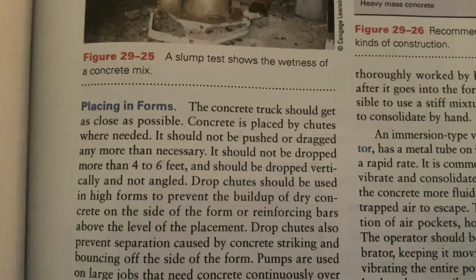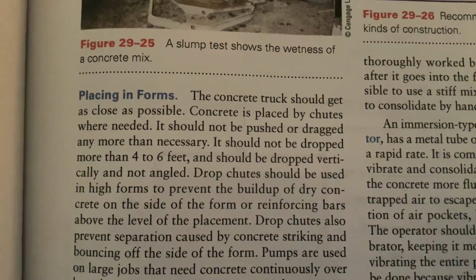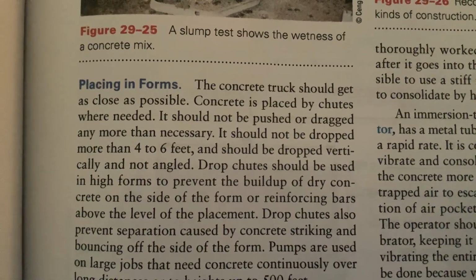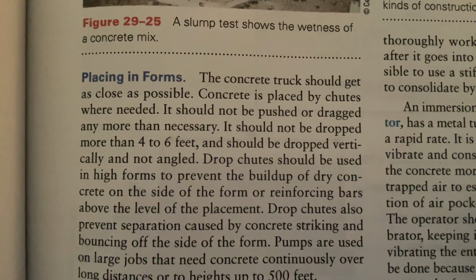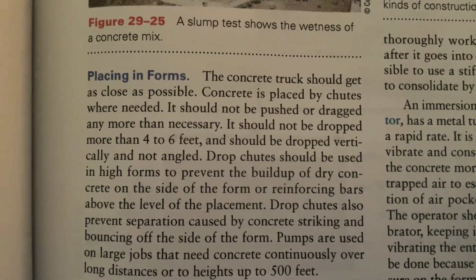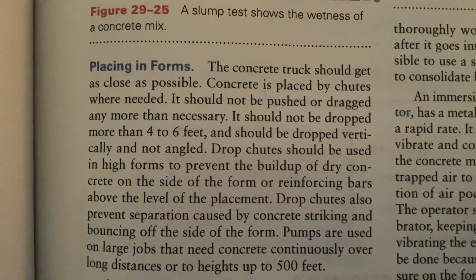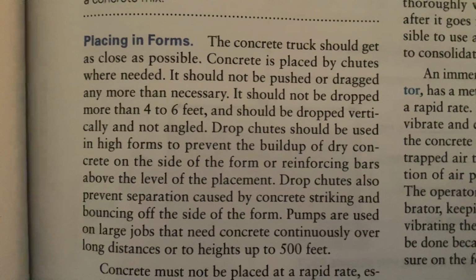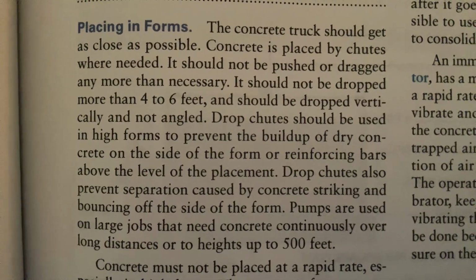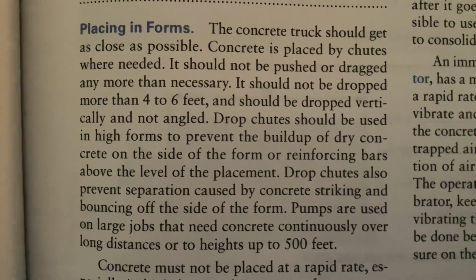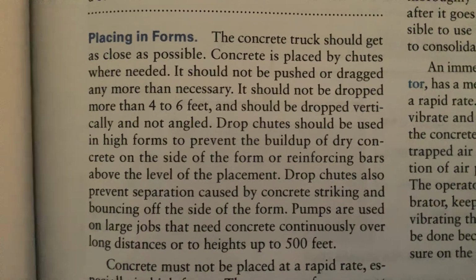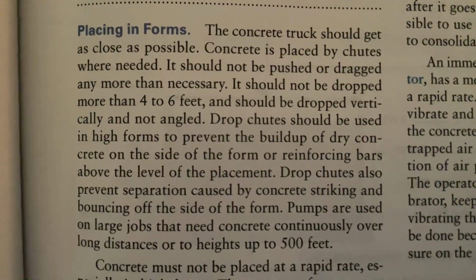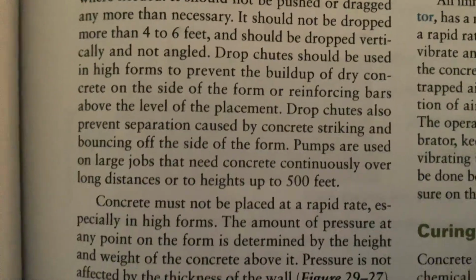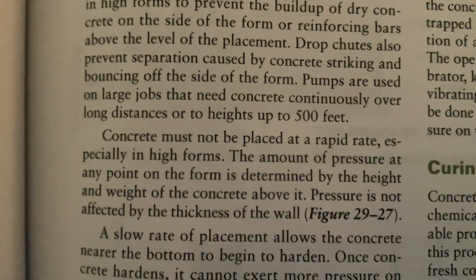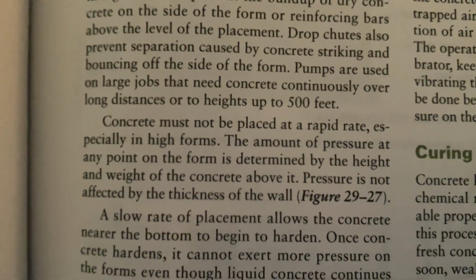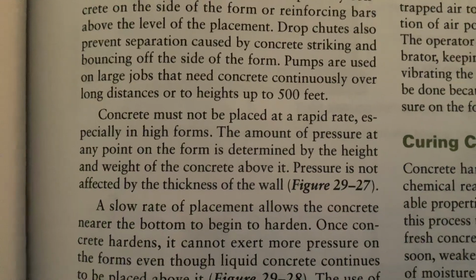The concrete truck should get as close as possible. Concrete is placed by chutes where needed. It should not be pushed or dragged more than necessary. It should not be dropped more than 4 to 6 feet, and should be dropped vertically and not angled. Drop chutes should be used in high forms to prevent the buildup of dry concrete on the sides of the form or reinforcing bars above the level of the placement. Drop chutes also prevent separation caused by concrete striking and bouncing off the sides of the form. Pumps are used on jobs where large amounts of concrete are needed continuously, over longer distances, or to heights up to 500 feet.